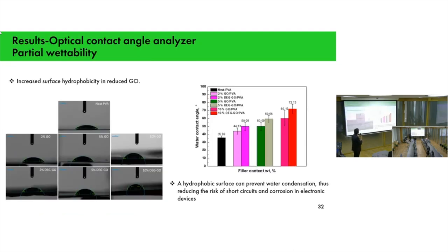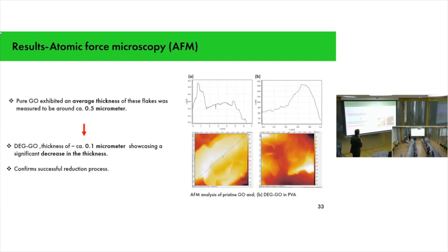So when talking about the PVA-based polymer system, we see that as we increase the concentration of our filler, like 5 to 10%, with the reduced graphene oxide, we see an increase in water contact angle, which is very important when you are dealing with short circuiting and especially corrosion in electronic devices. Moreover, in atomic force microscopy, you can see that our graphene oxide had an average thickness of almost 0.5 micrometer, but after the reduction, it reduced to 0.1 micrometer, showing a significant decrease in thickness. It also confirmed the successful reduction process.